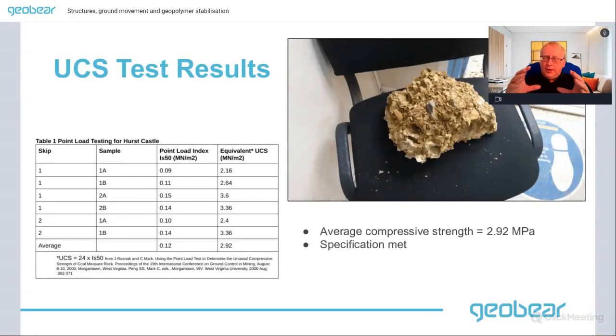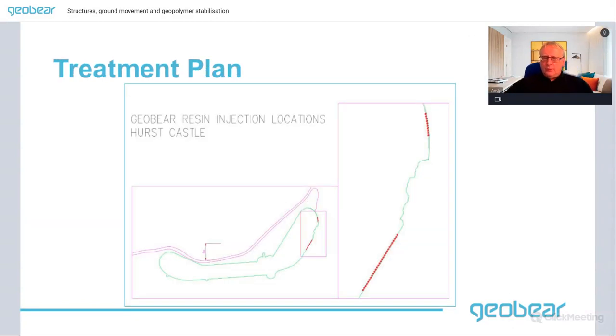We took some of the samples of this bulb of polymer, which was now a mixture of shingle from the beach and polymer. We had it tested in the lab, and we had an average compressive strength of nearly 3 megapascals. So the actual hardened polymer was really quite hard. So that also passed the requirements. Then, moving forward, we came up with a treatment plan, and that was to inject either side of the failed section to stabilize that prior to coming back and redoing the section that had failed.